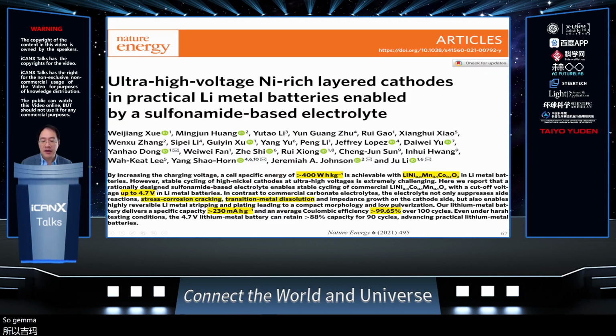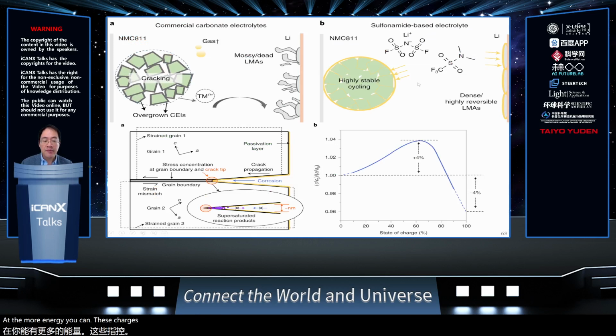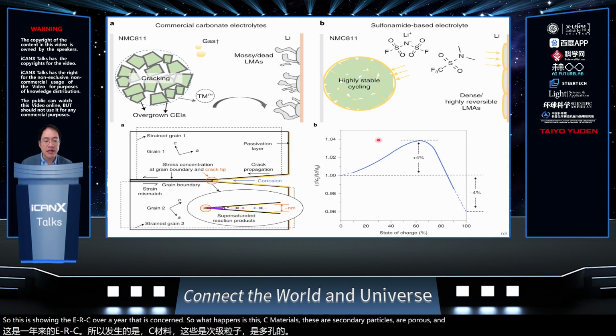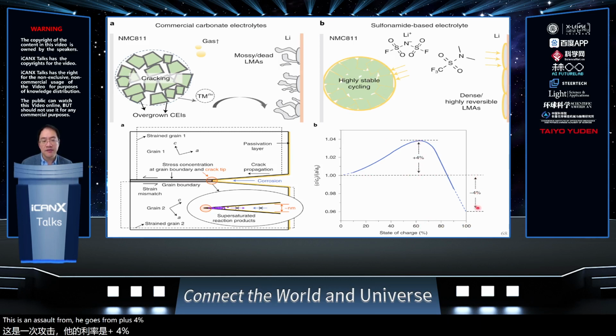So generally, we know that the higher the charging voltage, the more energy you can discharge. But usually the higher the charging voltage, there is more strain in the system. So this is showing the c/a lattice constant. So what happens is these NMC materials, these are so-called secondary particles, are porous polycrystals. So at the end, 100% of the charge, this anisotropy goes from +4% to -4%.